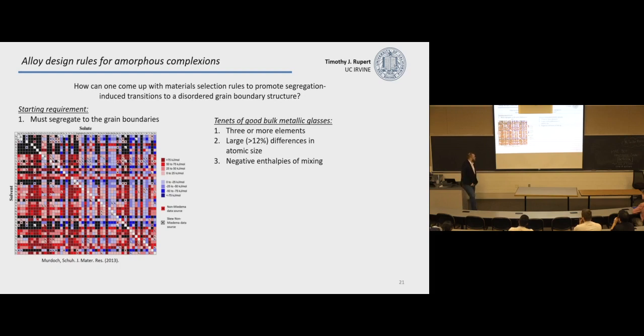So we thought about what was really happening and how can you promote these disordered grain boundary transitions. And we started to think about what would really have to happen. Well, the first starting requirement is you need to have segregation to the grain boundaries. So I said I want to add in alloying elements. I want them to go to the grain boundaries and change the structure. You got to have something that goes to the grain boundaries. If that's not true, then the idea falls apart.